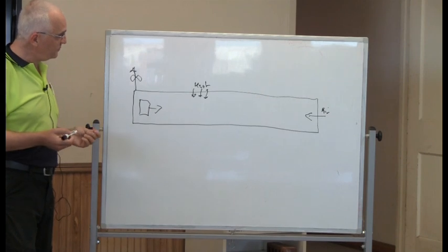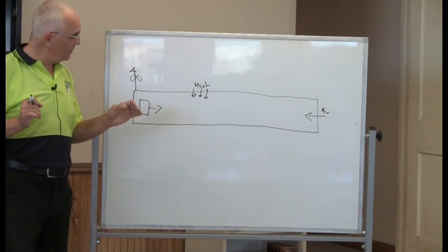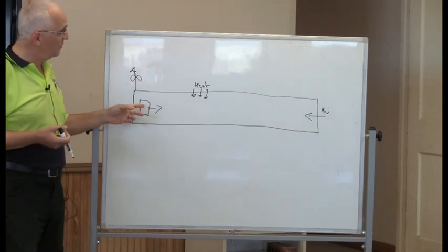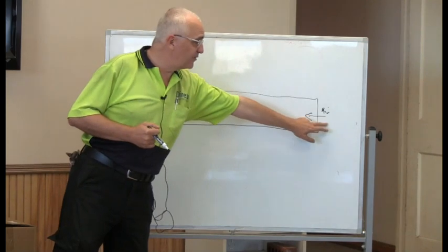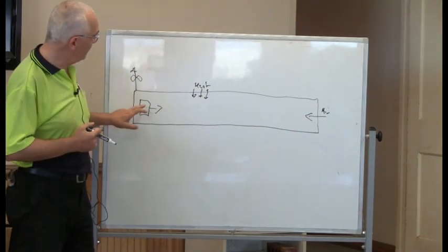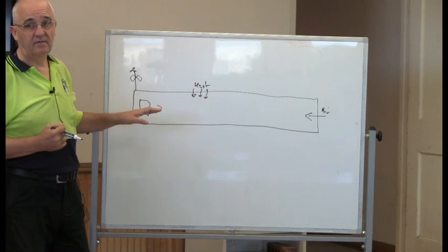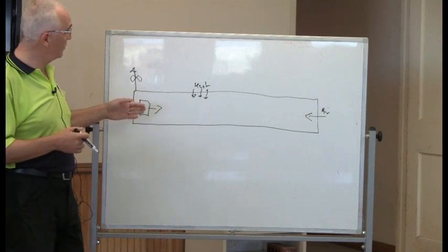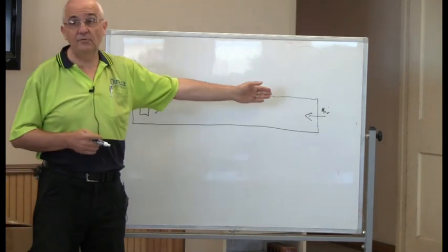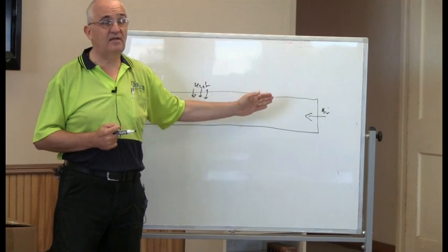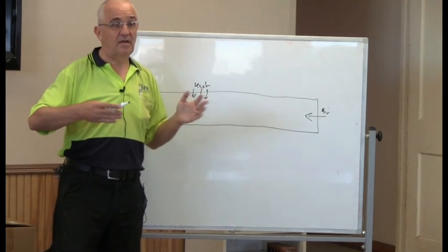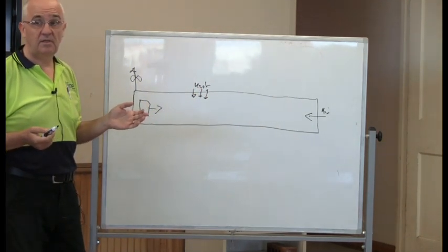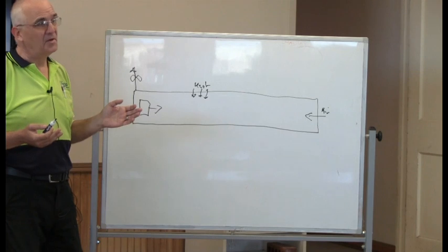The thing is, do we agree that, and I'm using the word mass because the pounds of air I'm supplying here are totally related to the pound of bricks I'm supplying there, okay? I have an ideal ratio, okay? So if I double that quantity of bricks, I need to double that quantity of air to achieve exactly the same effect in the cooling, in the preheat, in the firing zone. Right?